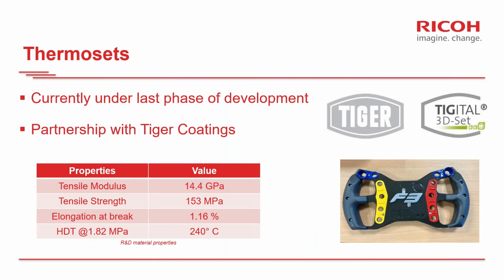So far we've seen mainly thermoplastic polymer matrix, but actually the process can also work with thermoset polymer matrix. For example, thermoset powders, like the ones that have been developed by Tiger Coatings under their TIGITAL 3D-Set range, can also be used in this process. And there is actually a collaboration, a partnership going on between Ricoh, Tiger Coatings, and Impossible Object. The main benefit of thermoset powders is the fact that they require lower processing temperature compared to thermoplastic powder, especially like PEEK. So the process speed is slightly faster than in the case of PEEK, for example.